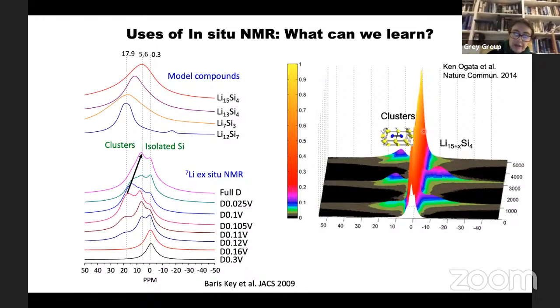This is an example where we're looking at tin as an anode material. I just want to turn the circle around and talk a little bit about the silicon. This was the first example of our work where we really figured out what was going on with silicon, and we looked at the type of structures that were formed in this material. But what was interesting was when we looked at model compounds and asked the question, what do the NMR signals of the stoichiometric compounds look like? So this is now lithium NMR. We got very different signals than we did when we made lots of batteries and examined their NMR.